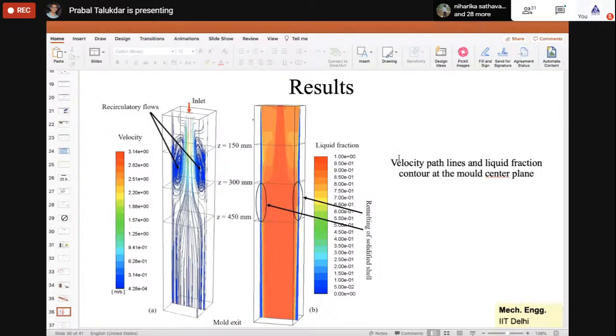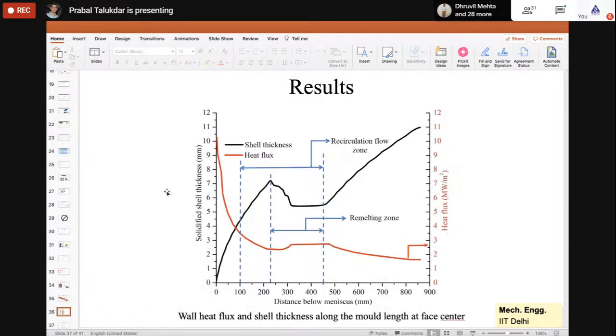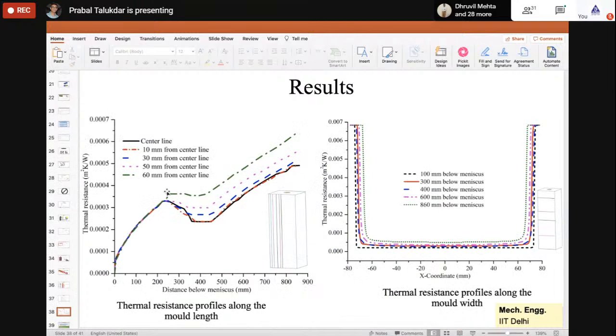The remelting, you can see here the recirculatory flows. The flow comes from the top, and because of the high velocity there is suddenly a recirculation here, and because of that the solidified shell starts melting on this side. So that is why the break, shrinkage and heat flux changes happen in this region, which is an interesting phenomenon which we have observed. No one has observed it in billet casting. People have observed it in other casting, but in billet casting we have observed this another important issue in this problem, right? So some of the results I'm not going to discuss any more.